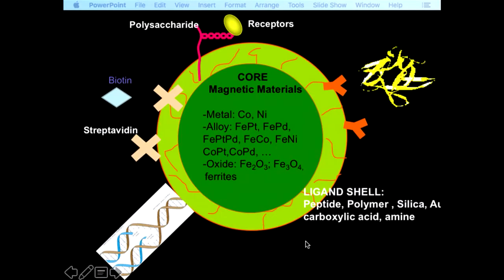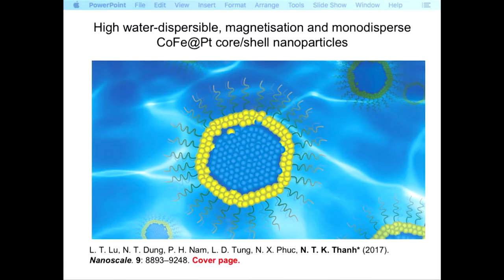So we design different types of nanoparticles. As I said before, we make them with a pure iron zero core. So what we need to do is have a coating to protect it from contacting with the oxygen. The iron cobalt is one of the class of alloys which have the highest magnetic moment. So we managed to make that, coat it with platinum, and later functionalize it with a polymer to make them water dispersible, to improve the current hyperthermia cancer treatment.